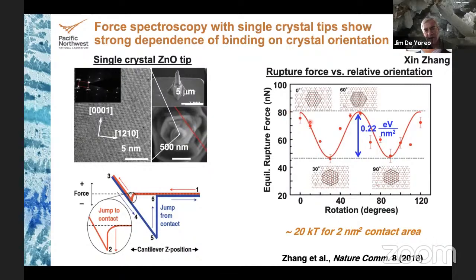And what you see is an oscillatory function, which is what you expect, with a maximum in the rupture force when you have alignment, and a minimum when you're misaligned. The difference here is about 0.22 eV per nanometer squared, which is about 20 kT for a 2 nanometer squared area. And that's the difference between being aligned and misaligned.